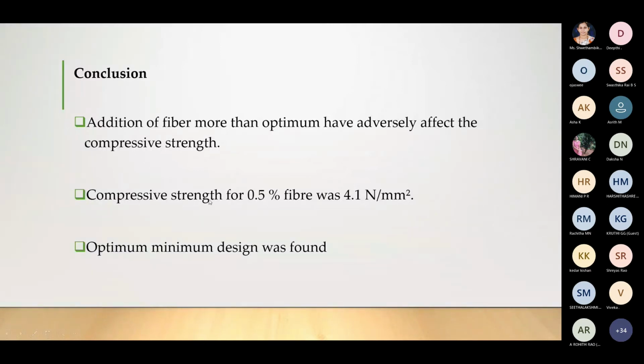Compressive strength for 0.5% fiber was 4.1 Newton per mm square. If you increase the fiber content, compressive strength will decrease. So the optimum mix design was found in this project, but compressive strength for 0.5% fiber was 4.1 Newton per millimeter square. If you increase the fiber percentage, compressive strength of course decreases. It is the result of this project.